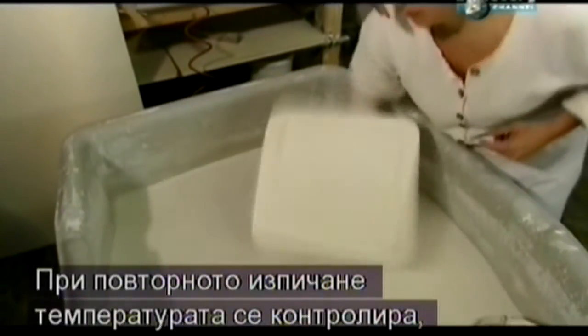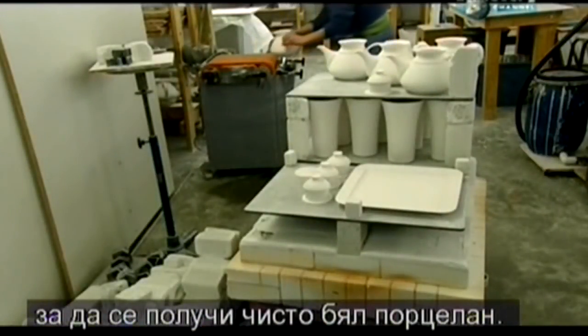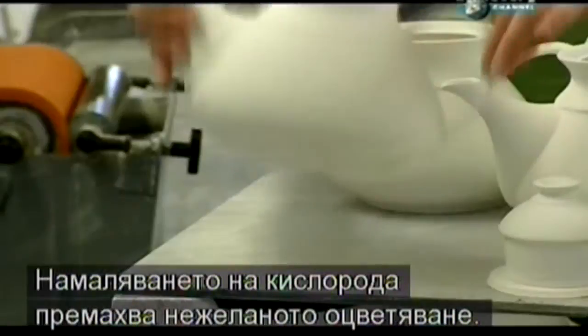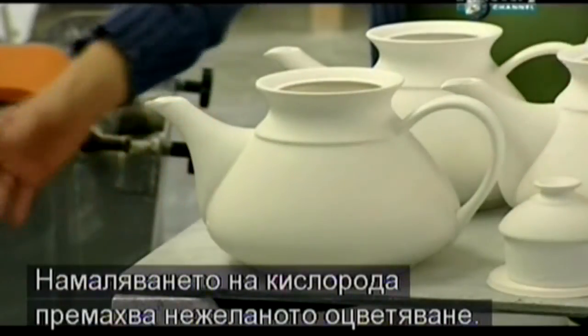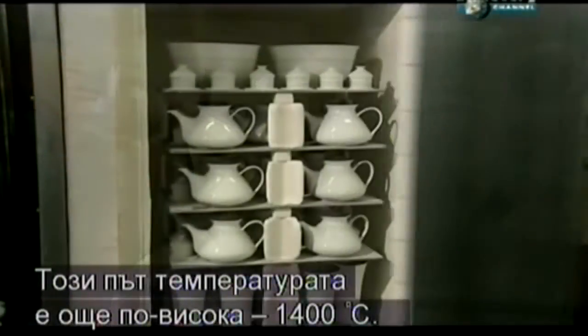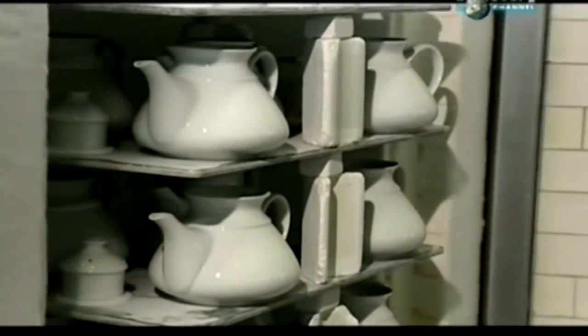During a second firing, the air in the kiln is carefully controlled to produce a pure white porcelain. Reducing the oxygen level removes any undesirable colours. This time the temperature is even higher, 1400 degrees Celsius. The pieces shrink by around 15%.